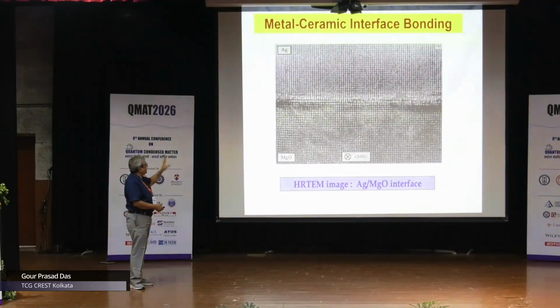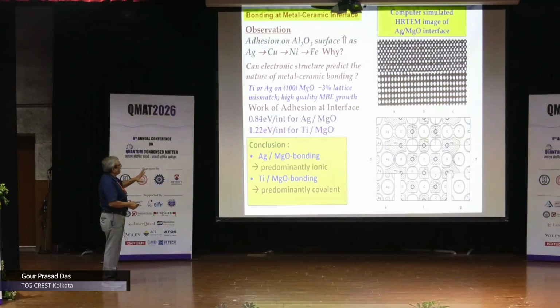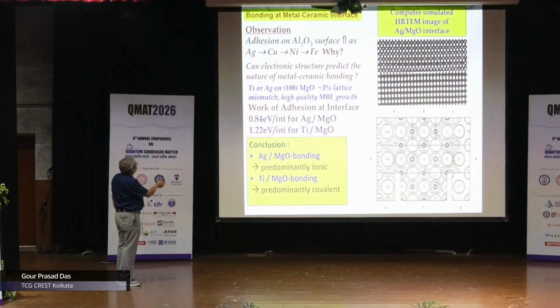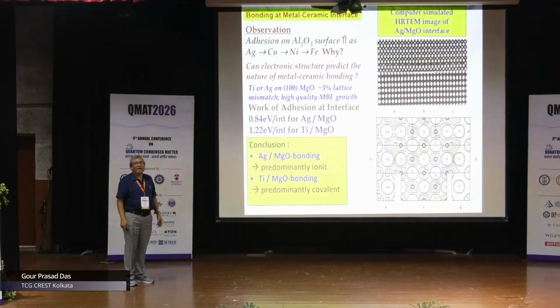Why? We did a very detailed calculation, and I'll just tell you the result: the adhesion on ceramics like Al2O3 or magnesium oxide changes as we go from silver to copper to nickel to iron. So this is a ceramic, and on that you are putting some metal in order to take the current out. But if it peels off, then it is useless. So as a function of the D band occupancy, we found that silver on magnesium oxide is bonded predominantly as an ionic bond, whereas titanium on magnesium oxide is predominantly a covalent bond, and the covalent bond is stronger.